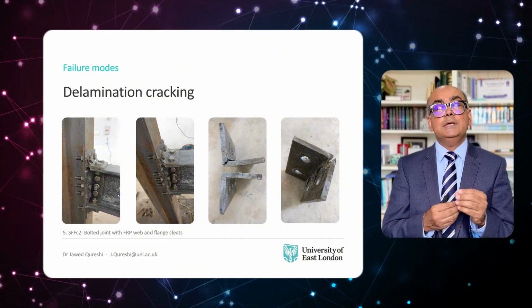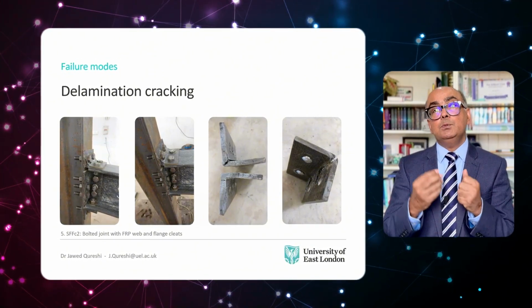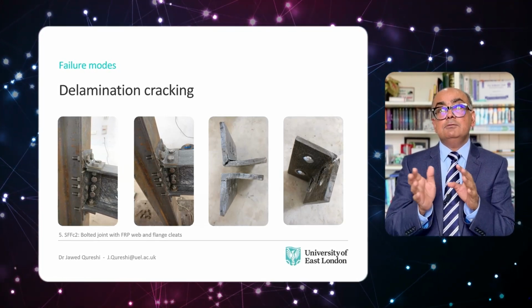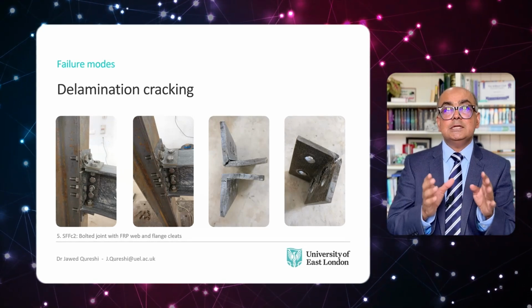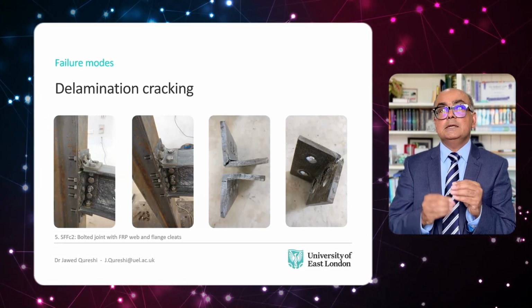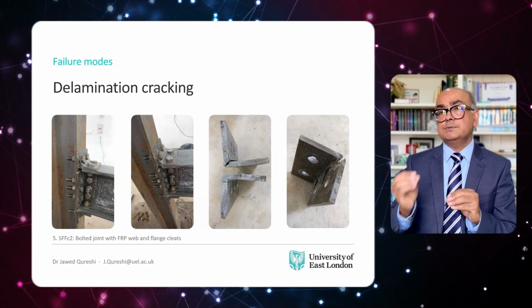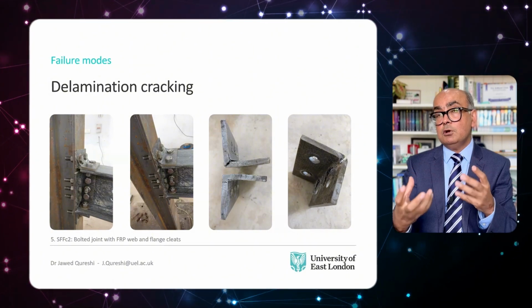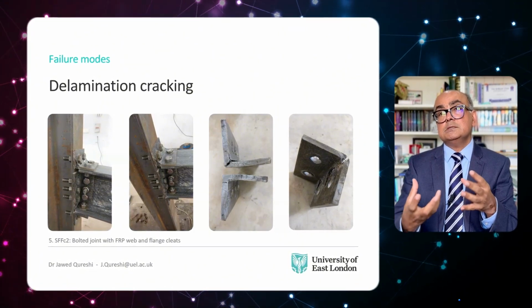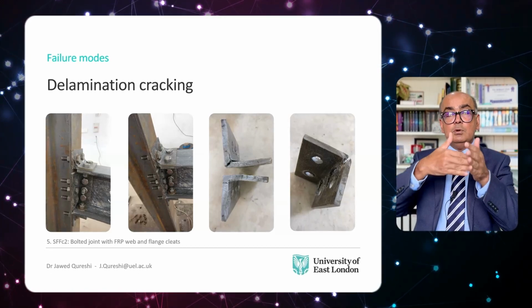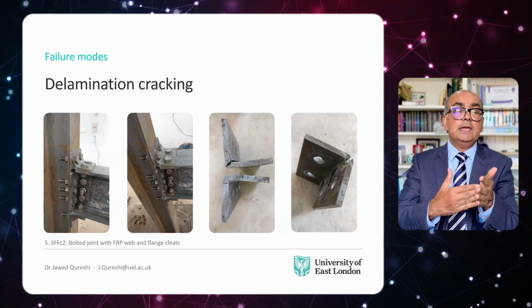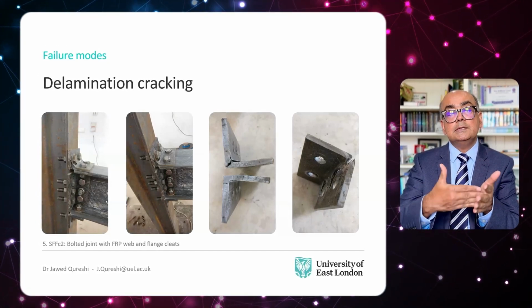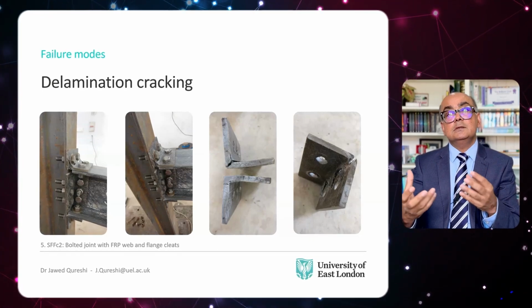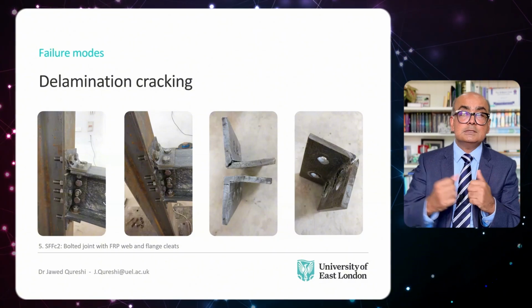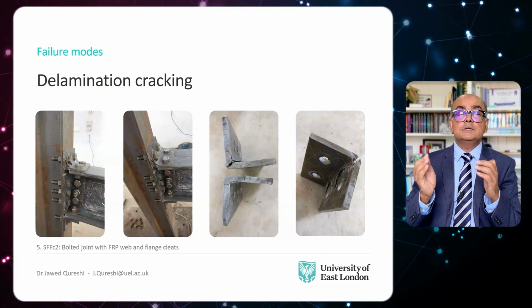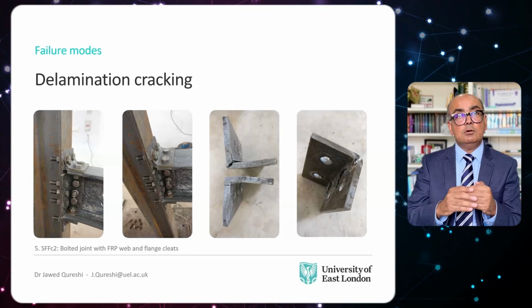Third and final failure mode is delamination cracking, and this happened when we used FRP cleats. And the failure mainly happened due to delamination cracks at root radius of FRP cleats. However, no cracks were observed on beam side. Now this is quite obvious when we use softer materials like FRP as cleats. When you apply a moment, first thing that will fail is the weaker material or weaker component, and that is FRP cleats. That is the reason we observed a lot of cracks, as you can see in this picture, and the specimen failed due to delamination cracking of cleats.